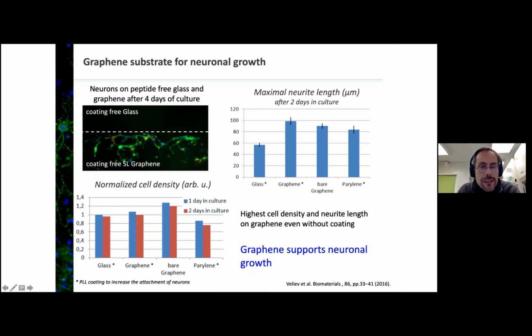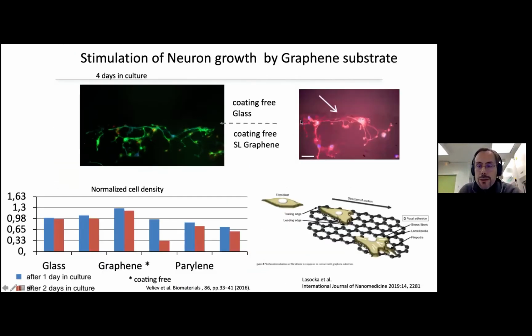As you can see here, this is the border between coating-free glass and graphene, and you see that the neurites like to follow the border but not interact with the coating-free glass, like if they prefer to stay on the graphene layers. And you clearly see that, for example, on this graph, this is silica and this is monolayer graphene on silica. There have been a lot of potential explanations of that. And in this paper here, you can see another possibility of this biomechanical matching, which is proposed in this paper about this way graphene is promoting proliferation and spreading of living cells.